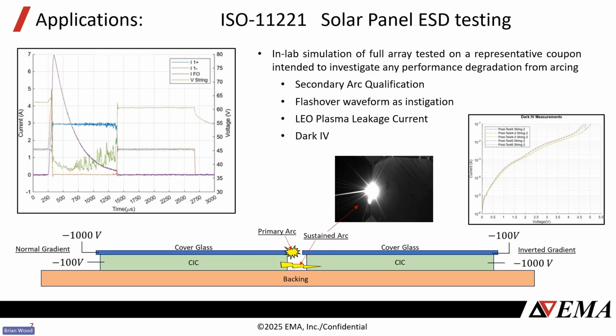Another example of something we can do that's also included in the ISO 11221 is this LEO plasma leakage current. And so say you've got a satellite that's operating in fairly high plasma densities, and the array is operating in the hundreds of volts range, that array can directly couple to the plasma and basically just leak current out into the plasma. And so that's seen as a current draw from your solar array. It's drawing power away from the spacecraft, and that's something that's undesirable.